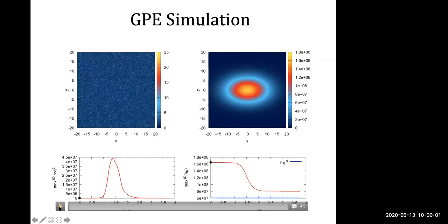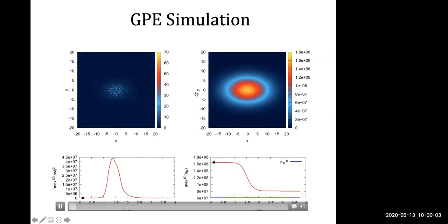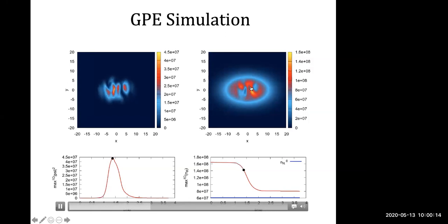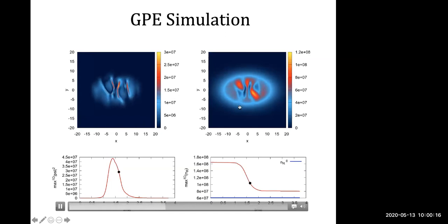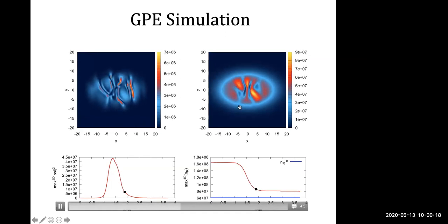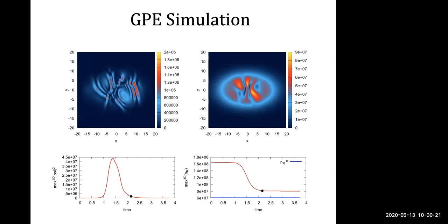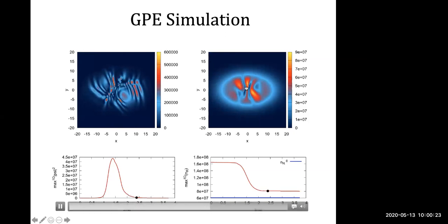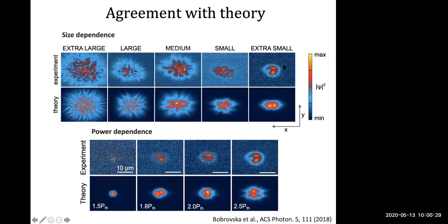This is shown here. So now you again have the nucleation of these little puddles of polaritons, but they persist long enough to spatially hole burn the reservoir density. And because you have this positive repulsive interaction, this creates attractive wells for the condensate, and the condensate just breaks up.